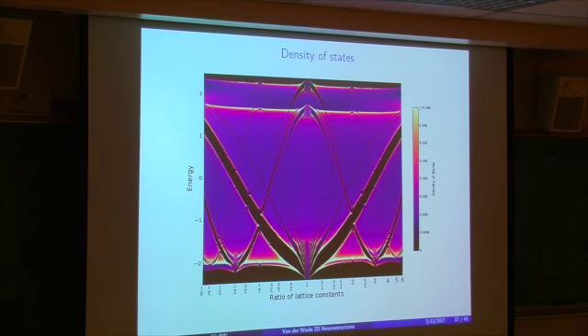So the main takeaway from this picture, I would say also, is that it's dangerous to make a computation for a small supercell. So say you have a system which is very close to being aligned, like boron nitride and graphene. And for computational purposes, it's easier to tweak them to have a periodic structure, to make them with the same lattice constants. This way you can make a simple periodic one-size cell that contains both lattices. And you go like, well, I didn't push too much, so this must be correct, and I will get a nice result. What this picture tells me is if I look a little bit away from 1, I have a very different behavior than if I'm exactly at 1. So just a small difference can make an actual big difference in the overall picture.